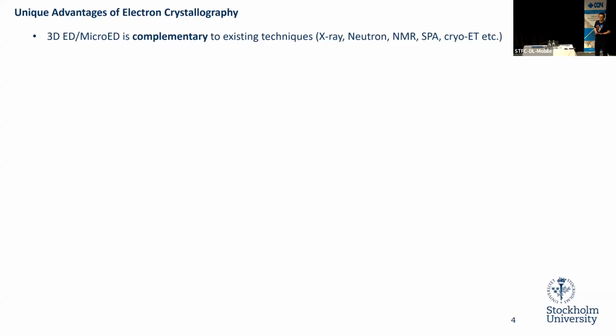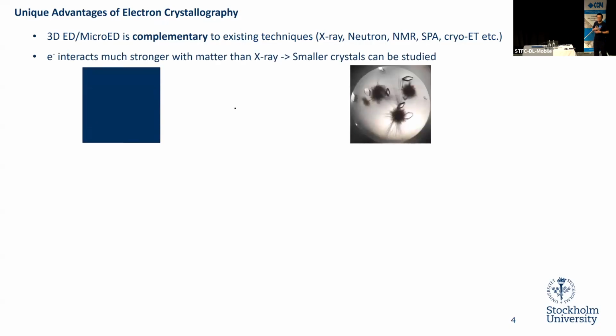Because of the development of X-ray crystallography and single particle cryo-EM, we're actually learning a lot from these fields, and that's why MicroED has developed really quickly in recent years. One of the major reasons we want to use electrons as the diffraction source is that we can work with much smaller crystals, because of the strong interaction between electrons and the crystal. A couple of talks ago, you heard the speaker struggling with needle crystals in a droplet. We actually love this kind of crystal. The large single crystals you use for X-ray are way too large for us, and we work with these very thin needle crystals. I can show you how easily we can collect data from them.